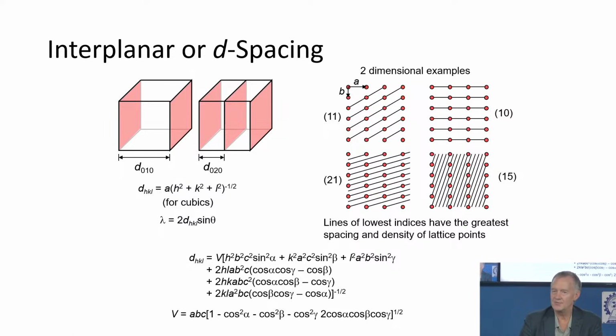When we talk about diffraction, a lot of times we'll work in reciprocal space. I don't know if somebody's going to cover reciprocal space. But the reason we do that is if we have spots in TEM that we're observing, then we'll see one spot that's a 010. If we move to the next spot, it's a 020. If we move to the next spot, it's 030. So that spacing gets larger. But the interplanar spacing is actually smaller. So we're in reciprocal space, so it goes larger. Okay? Good.